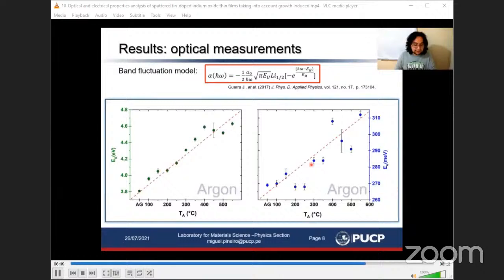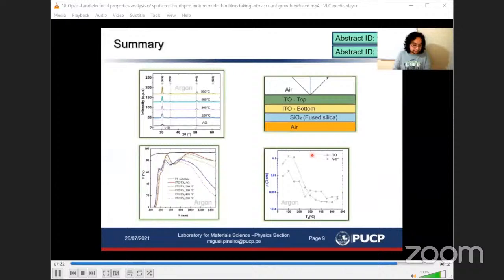They were calculated by using band fluctuation models. We can see in the left figure the widening of the energy bandgap caused by the Burstein-Moss effect. It is related to increasing carrier density. Now, in the right figure, we can also confirm that the Urbach energy is increasing with annealing temperature. So we may expect the defects are increasing, since the Urbach energy indicates the degree of disorder. The red line is a guide to the eye.